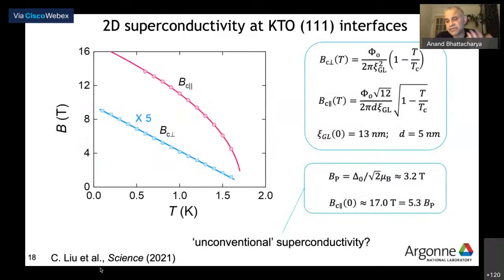And in fact, that's what we find. The critical field for out-of-plane looks like a straight line as a function of temperature. Cooling down, it just rises linearly. And the in-plane one, for field parallel to the film, has this square root dependence. This is all very standard for two-dimensional superconductors, so we just confirmed it. And we were suspecting all along that this was two-dimensional.